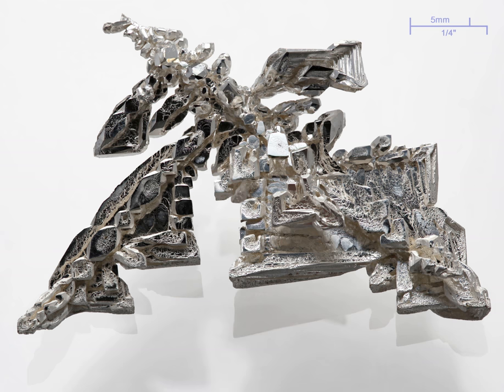Ag-C sigma bonds may also be formed by silver(I), like copper(I) and gold(I), but the simple alkyls and aryls of silver(I) are even less stable than those of copper(I), which tend to explode under ambient conditions. For example, poor thermal stability is reflected in the relative decomposition temperatures of AgMe at -50 degrees Celsius and CuMe at -15 degrees Celsius, as well as those of PhAg (74 degrees Celsius) and PhCu (100 degrees Celsius).